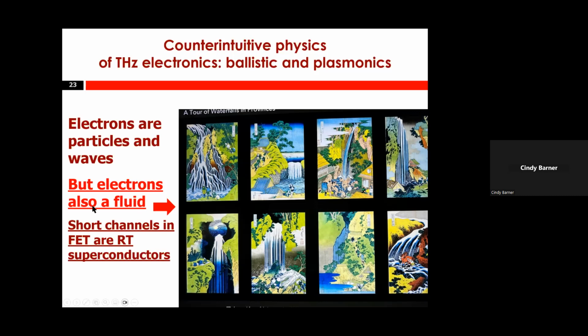Another new point that I want to make: you know that there is superconductivity at lower temperatures, but a channel of a semiconductor device, if the channel is short enough, is a room temperature superconductor. Why? You could understand it in this way. Inside of a semiconductor device, electrons move with the thermal velocity because of thermal energy. Therefore, on average, they spend very little time inside of the device, and during this time, they might not have enough time to collide with impurities or lattice vibrations. It takes a certain length called the mean free path for an electron to collide. If the channel is much shorter than the mean free path, there are no collisions. And we have to account for that. It has absolutely dramatic consequences.